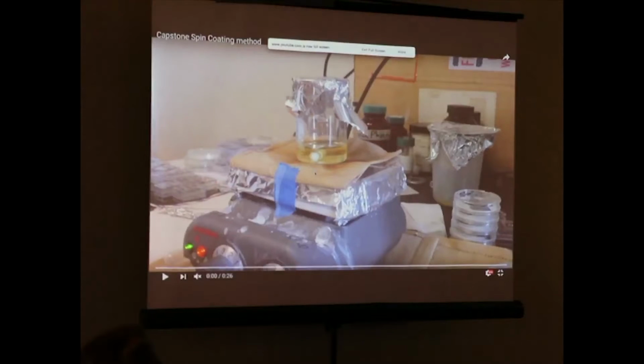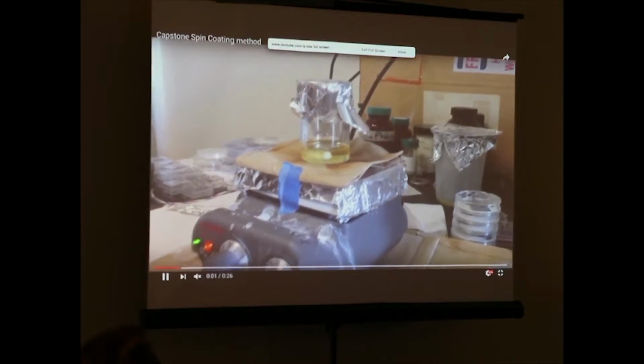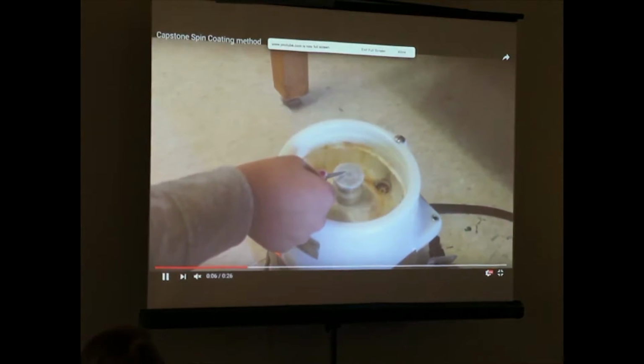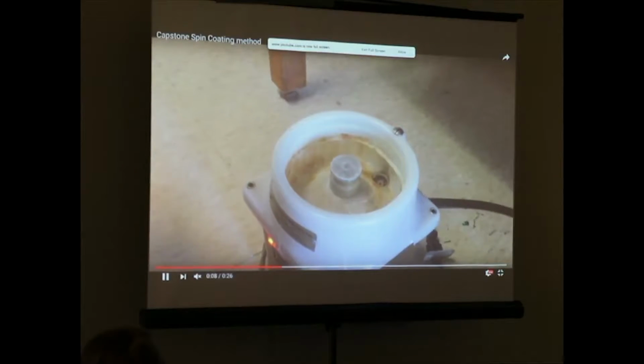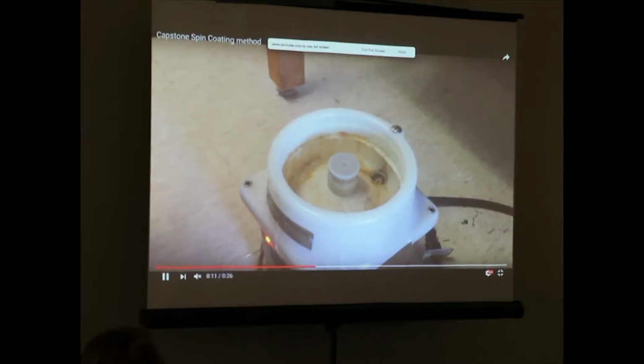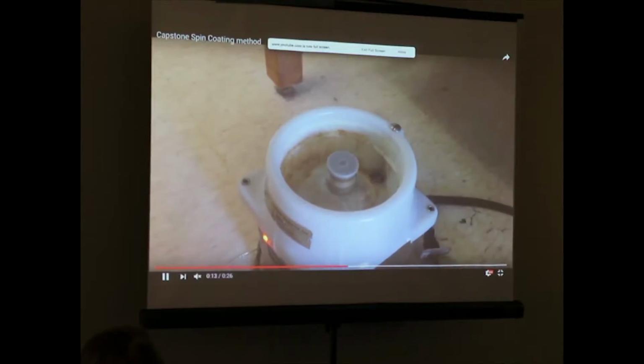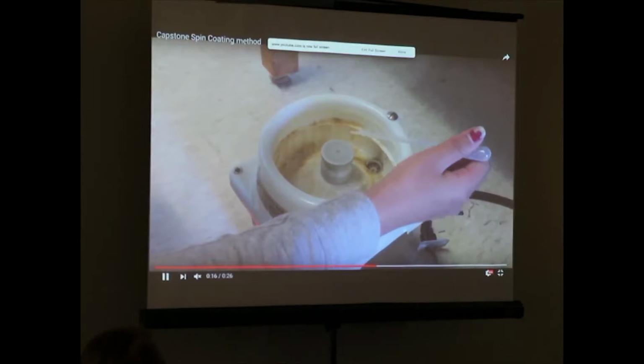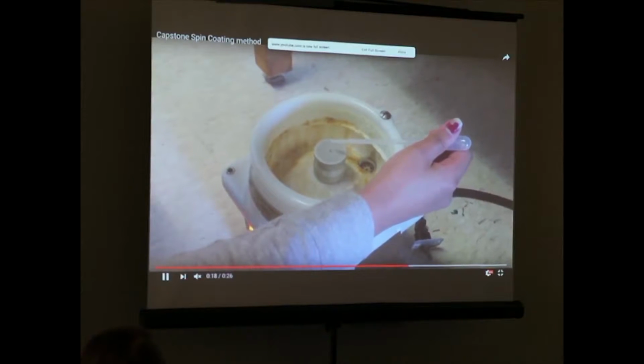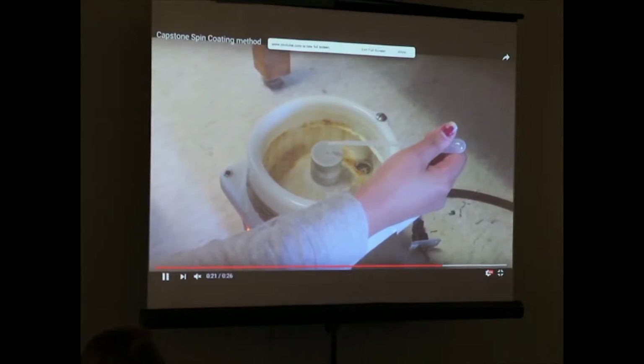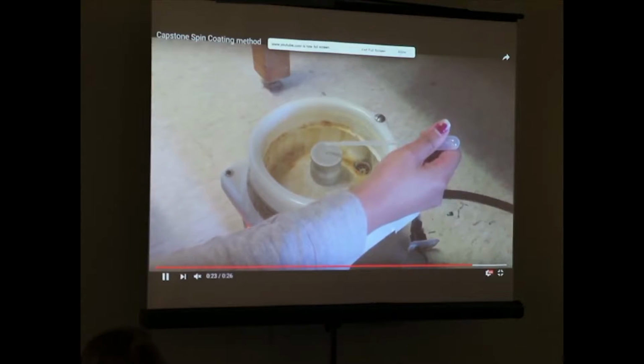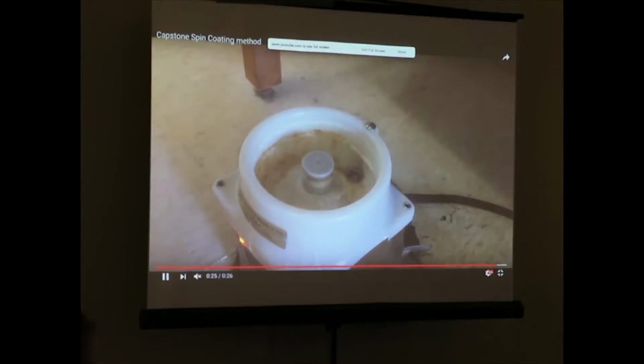And so here we have my solution, and it's being mixed and heated because we find that it helps actually glue it essentially to the glass a lot more efficiently than when it's cold. Then I place the glass on the silicon wafer, and there's a little hole so it sucks it in and holds it in place. And then I press the pump, and it spins about 2,000 RPM. And then I get a pipette, it's plastic, and I just drop it. So it's a fairly simple process. And you can see the little drops. What we're hoping is that it's uniformly coating the sample as it's rotating.